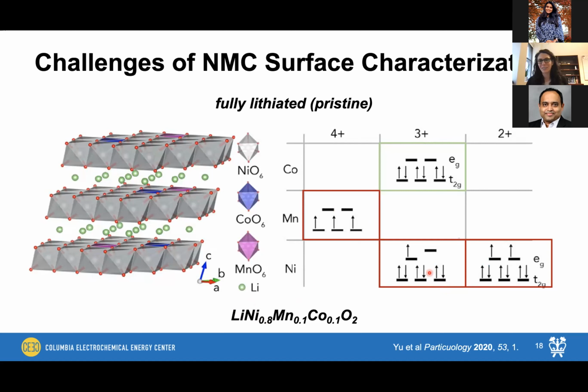This is not a good starting place if we actually want to be able to analyze the surface chemistry of whatever is appended to NMC811. Manganese is in the 4+ oxidation state, also paramagnetic, not helping us. The only thing we really have going for us here is the fact that our cobalt is in the 3+ oxidation state. This is diamagnetic, but cobalt really only makes up 10% of our transition metal centers here. So it's really not going to be that helpful to us. Most of our material is very strongly paramagnetic here. So the chances of us getting highly resolved NMR signal here is highly unlikely.